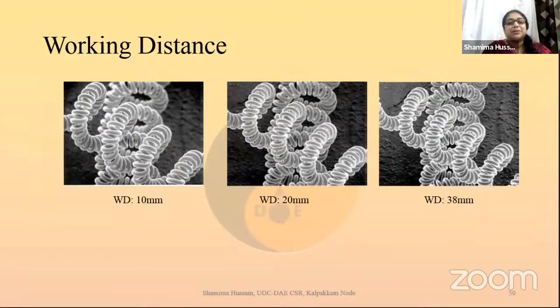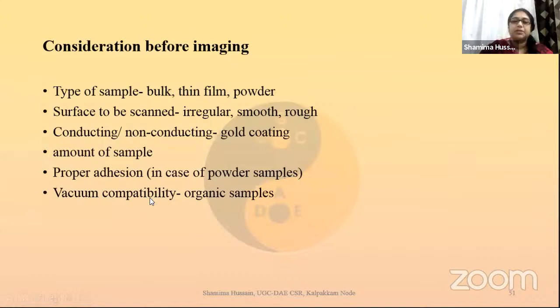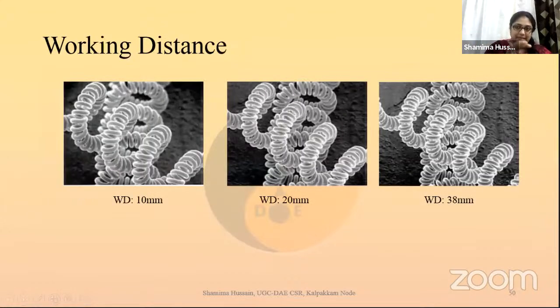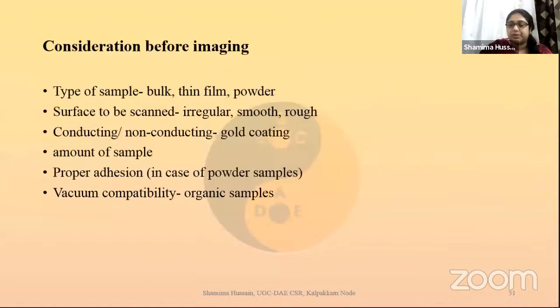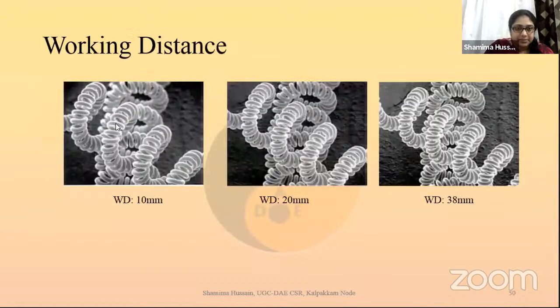So here is something on the working distance only. The same sample, I have had three different working distances. If I keep it at 10 mm, that is the distance between the pole piece to my sample surface is 10 mm, then the features look like this. Please see the spread. This is the dimension of the sample that we are viewing now.